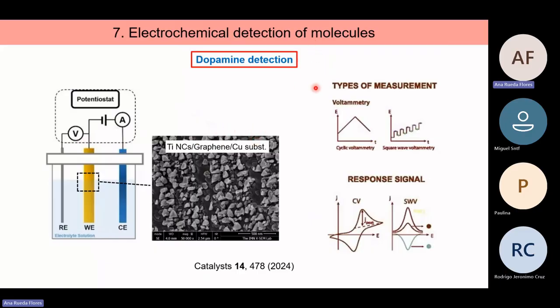And we will use two typical types of measurement. Cyclic voltammetry: voltage as a function of time having this shape, and this is the typical response of the current as a function of the voltage. And we can focus on one of the peaks, and we can then perform square wave voltammetry with this profile, and this is the typical shape of the curves.